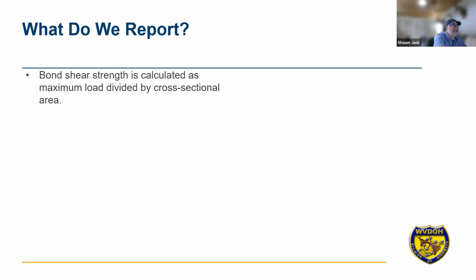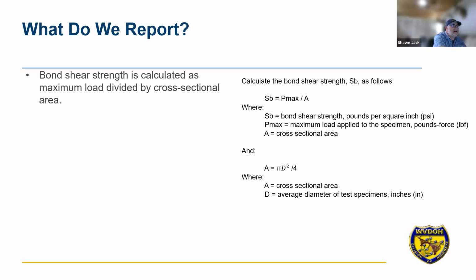So bond shear strength is calculated as the maximum load divided by the cross-sectional area. I've included the actual calculations that we use here in case you're interested. But in order to calculate bond strength, you need to know the maximum load applied to the specimens in pound force, which is the information that you're going to get from that Marshall stabilometer, and the cross-sectional area. And in order to determine the cross-sectional area, we use pi times the diameter squared divided by 4, and we average the diameter of the test specimen. We take four measurements on that test specimen and average that.